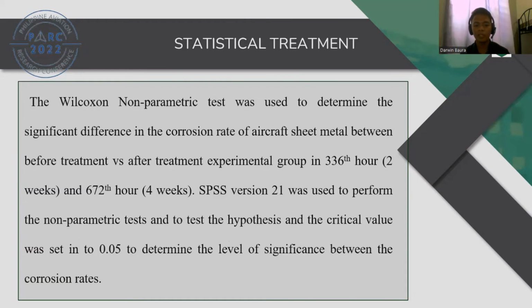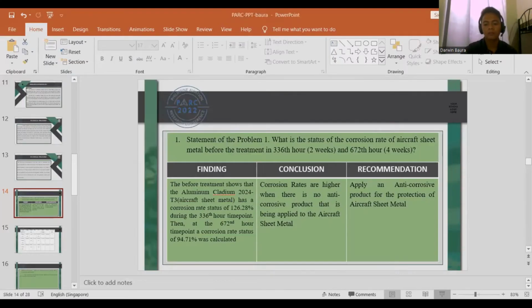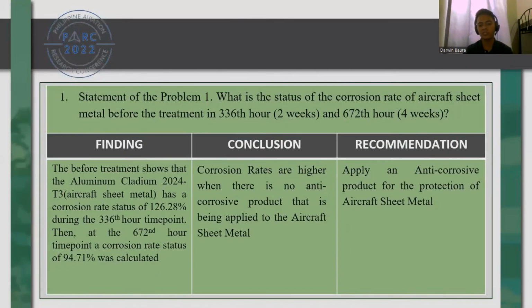So the Wilcoxon non-parametric test was used to determine the significant difference in the corrosion rate of aircraft sheet metal between before versus after the treatment at 336 hours and 672 hours. SPSS version 21 was used to perform the non-parametric test and to test the hypothesis, and the critical value was set at 0.05 to determine the level of significance between the corrosion rates. So let's proceed to the results and discussion.